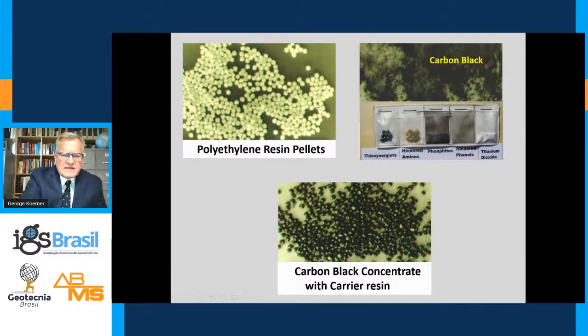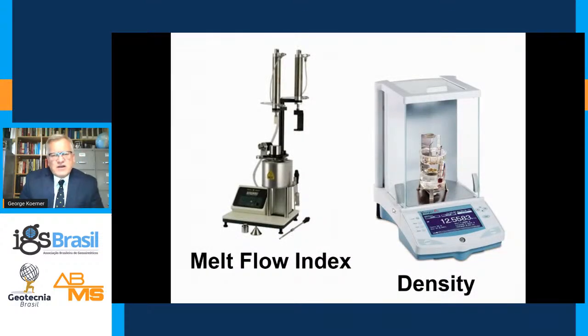Here you see the polyethylene pellet, which typically arrives in rail cars or gaylords at a facility. You would like to mix the carbon black, but please realize these additives and the carbon black, the blocking agent, are typically in powdered form. Therefore, they're typically mixed with a carrier resin and form what's known as a concentrate. A manufacturer needs to assure that this material is quality material and conforms to his internal specs. He or she also wants to make sure that this material is good material and what he paid for. So typically the quality assurance before the manufacturer will release this material into his silos at the plant is twofold. One is melt flow index and the other is density. They'll do these cursory checks to make sure the material is quality and what they're paying for.